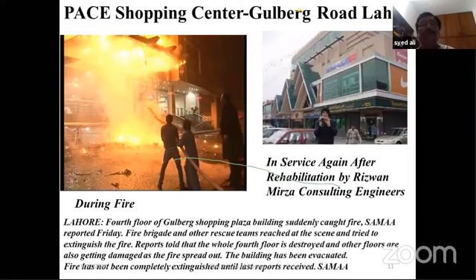And we took out the samples of concrete and reinforcement. To our utter surprise, and interestingly, the reinforcement was grade 60 cold worked steel. The cold worked steel has original grade 40 steel, but after cold working, it attains grade 60. But if the temperature exceeds 400 degrees centigrade, the grade of steel drops from 60 to the original 40 billet grade. So that again reduces the margin of safety.